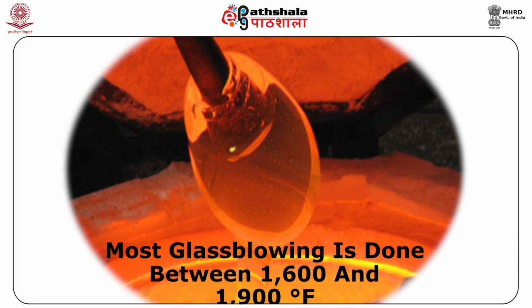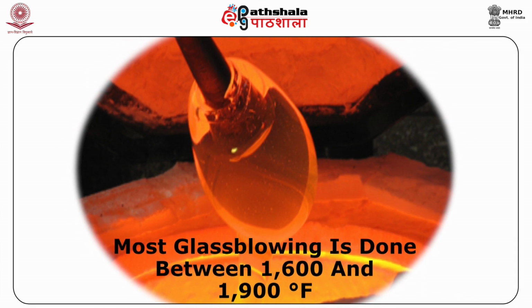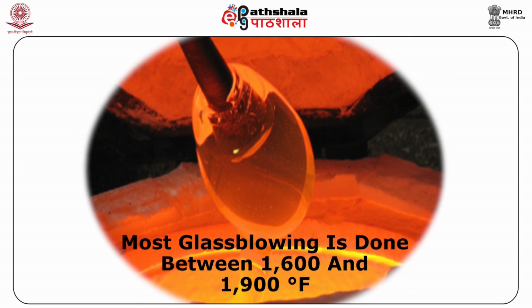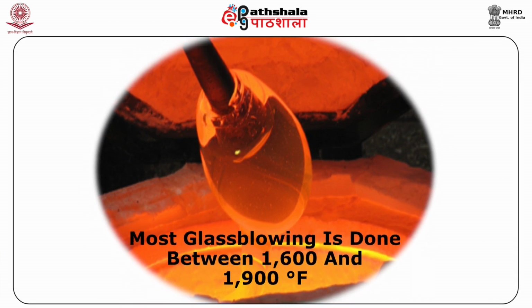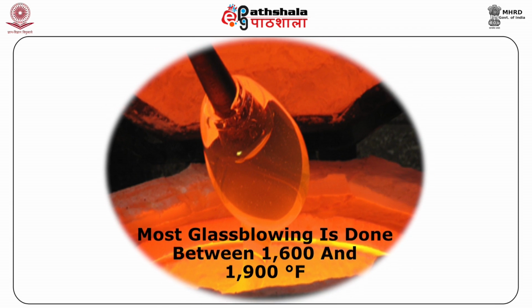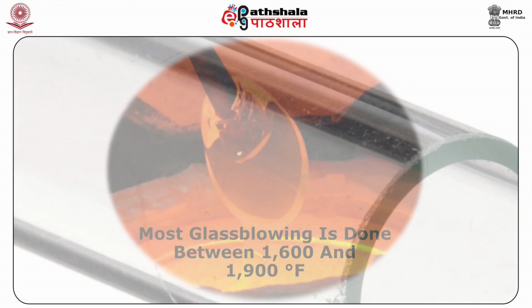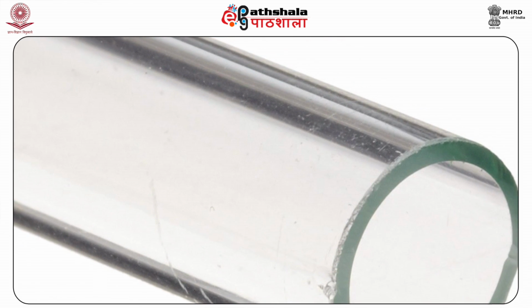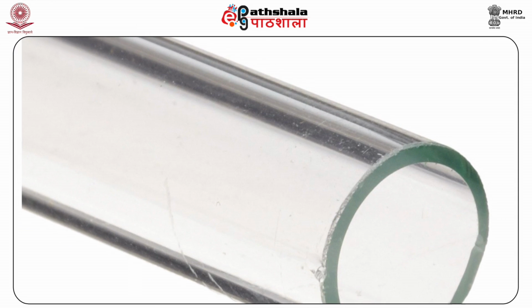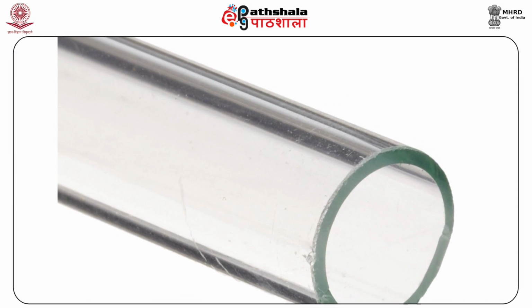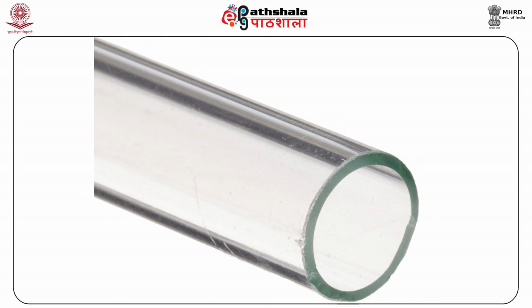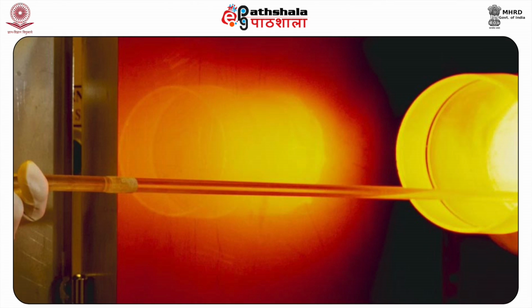Though most glass blowing is done between 1600 and 1900 degrees Fahrenheit, that is 870 and 1040 degrees Celsius, soda lime glass remains somewhat plastic and workable as low as 1300 degrees Fahrenheit, that is 730 degrees Celsius. Annealing is usually done between 700 and 900 degrees Fahrenheit, that is 371 and 480 degrees Celsius.